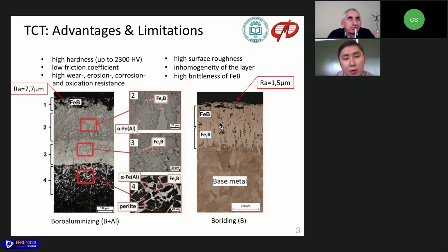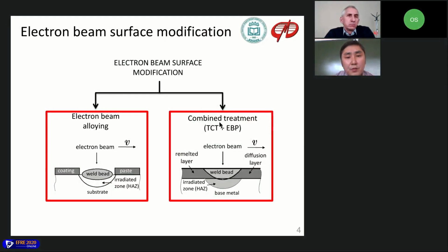So the advantages of these two processes are high hardness, up to 2300 HV, then low friction coefficient, high wear, erosion, corrosion, and oxidation resistance. And disadvantages are high surface roughness, as you can see on both pictures, and inhomogeneity of the layer. On the left picture, you can see a complex microstructure divided into several sublayers, and each sublayer has its own phase composition and morphology. So this is a negative property, and one of the huge disadvantages is high brittleness of the iron boron phase, which is on top of the layer. So these limitations encouraged us to conduct research in electron beam surface modification.